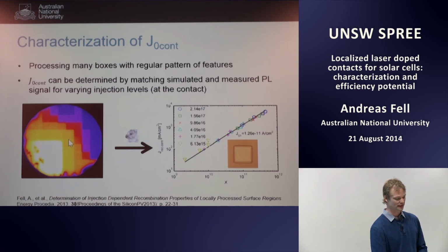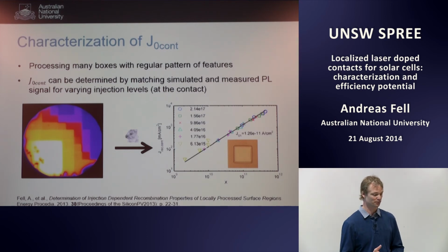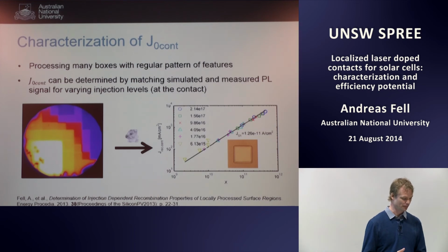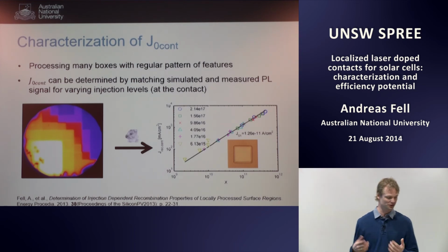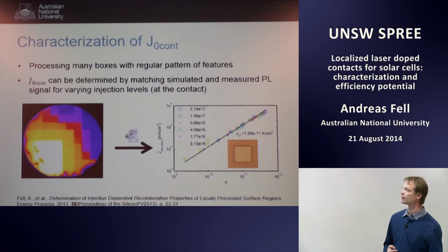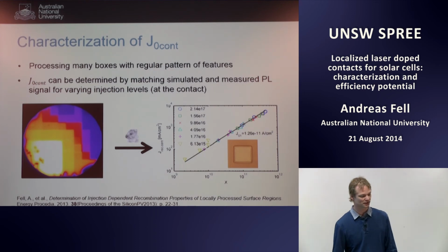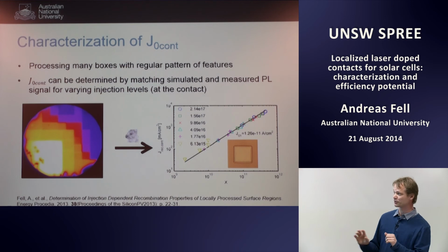So in this example, we fit like 7 laser parameters on a 4-inch wafer with different pitches, which is still plenty compared to if you would do the same thing by QSSPC, which you could do. That means for each pitch and laser parameter, you would have to symmetrically process a whole quarter of a wafer. And we also take care that we create a smooth gradient of the PL images to suppress smearing effects or to make them less effective.